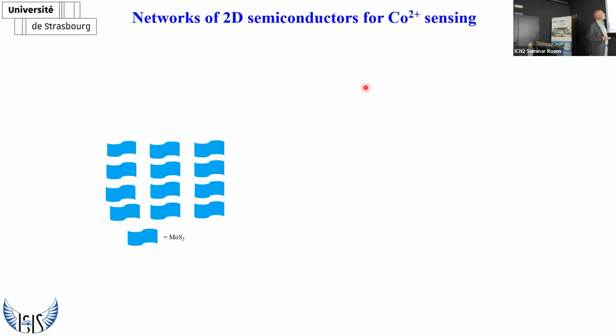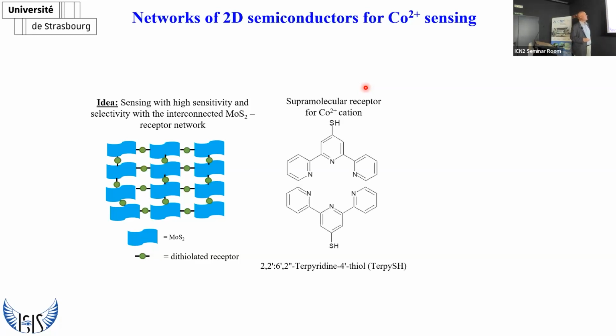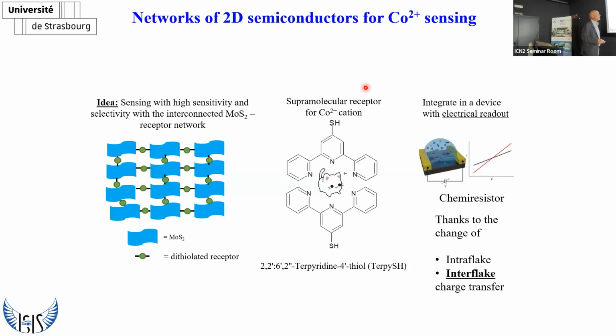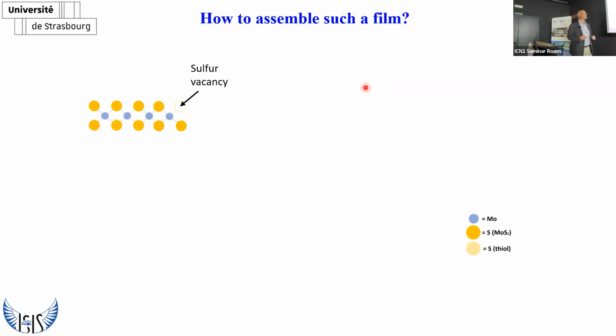And for example, very recently, we have been working on a project in which we use MoS2, and we wanted to create a network with a doubly thiolated receptor for chemical sensing. And so actually the receptor is quite banal, and also the analyte is quite banal. We use terpyridine, and actually we use this for cobalt ion sensing. And we utilize an electrical readout. In particular, you can imagine that upon treatment of the flakes of MoS2 with this kind of molecule and successive complexation, you can modify the charge transport both at the intraflake level, when eventually the functionalization is within the flake, or at the interflake level, where you can have the transport through a receptor with or without the metal center. So I will show you just the approach, not the result,